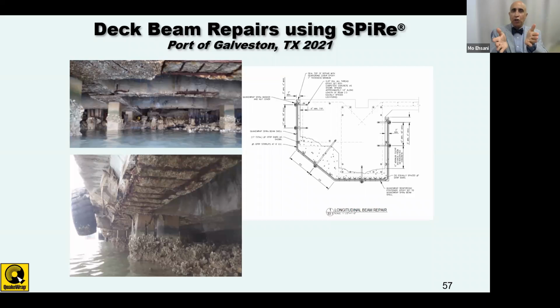So what we can do is custom make this FRP material to fit the exact shape of the underside of the pier. We can also include some additional reinforcing bars if needed, and then from the underside they're lifted and bolted in place so they remain secure while the grout is poured, pumped from the top or from the bottom.